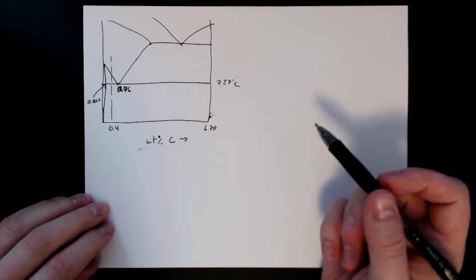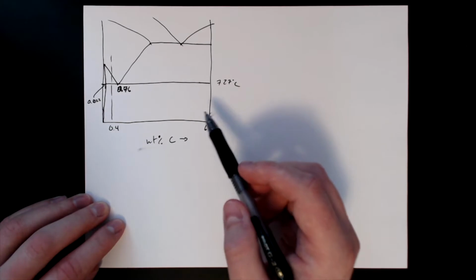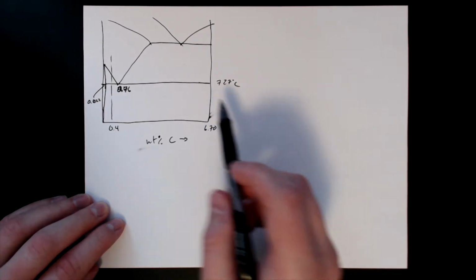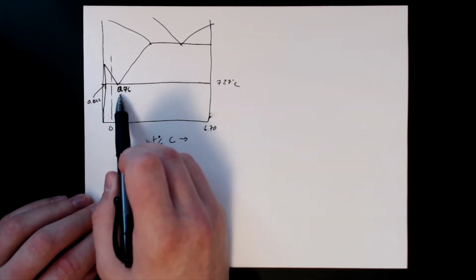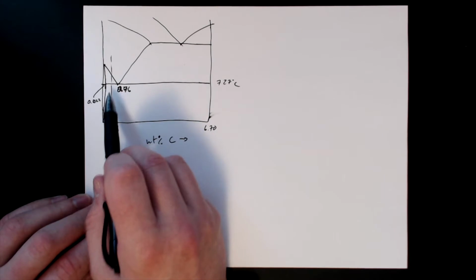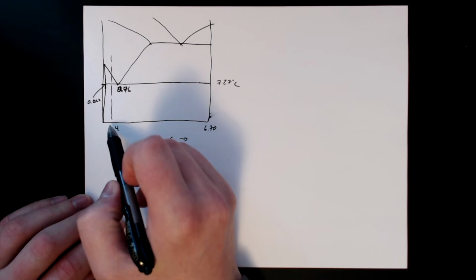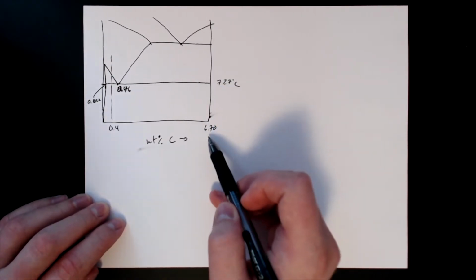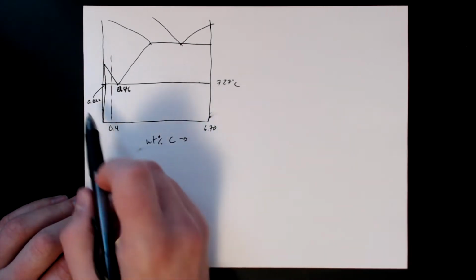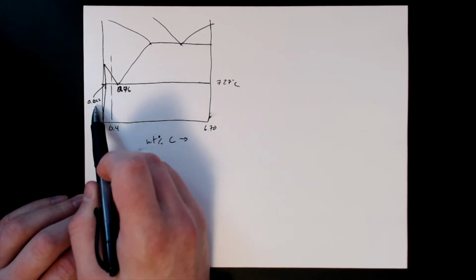All right, so I've tried to replicate the iron carbide system here. Probably not super well, but a couple things to note. I haven't really drawn the top part, so really we're just going to focus on the eutectoid, which is at 0.76, and then we have a composition of 0.4, which puts us over here roughly. And this is the eutectoid at 727, and we have cementite at 6.7 weight percent carbon, and then the max solubility at the eutectoid of alpha, which is over here, of 0.022.